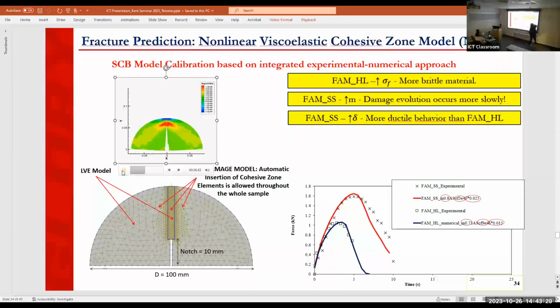So we did this calibration for the two samples. And from the difference of the parameters, we could get three things here. Sigma F was higher for the mixtures with hydrated lime, which is this one. The higher sigma F is related to the material being more brittle. That makes sense given the SCB test that we did, where hydrated lime presents more brittle fracture behavior, a very steep post-peak decay curve.